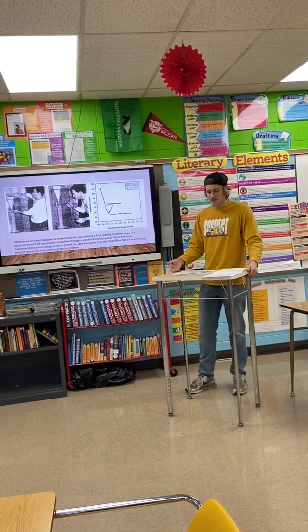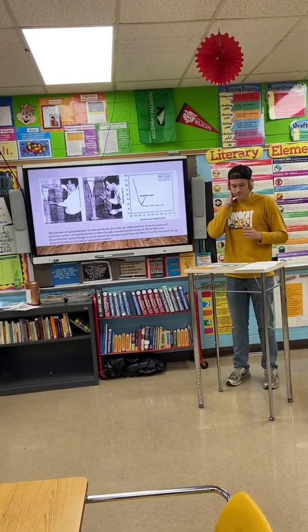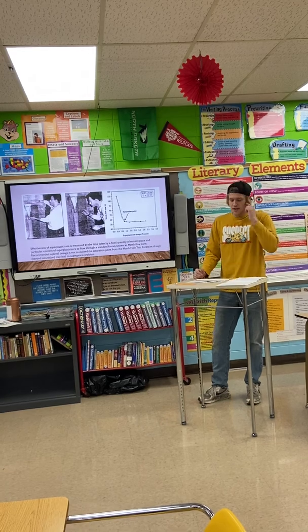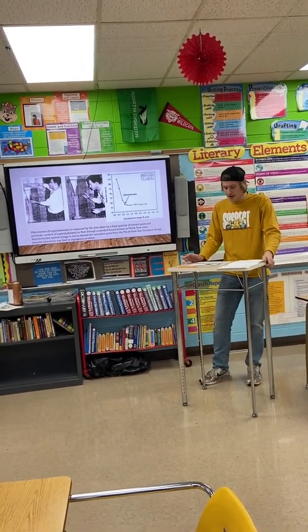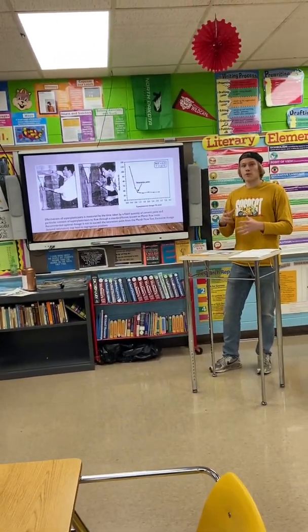The Marsh cone test is essentially running a fixed quantity of cement paste and particulate content of superplasticizers through a standard funnel, and based off of this funnel and concrete test, they give you a recommended optimal dosage for what you're looking for.